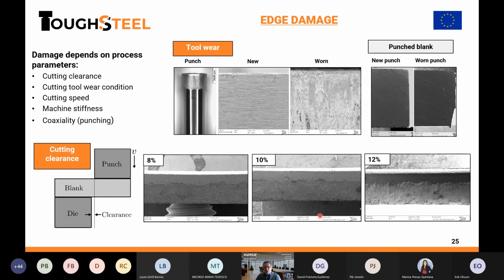Is this damage happening always, or is it difficult to control? Yes, this damage is present in a large production or serial production process. Damage comes from many places. Cutting clearance should be well adjusted. Cutting clearance changes with cutting tool wear. If we change the wear conditions, you see how the fracture of the sheet looks with a new punch and with a worn punch, because the effective clearance changes. Clearance clearly affects the fracture surfaces of a sheet.